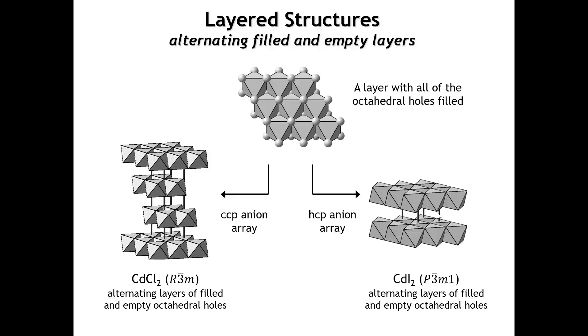In an ionic compound, filling cations in some layers but not others does not maximize cation separation, which is a clue that these are not truly ionic structures. What holds the layers together is typically dispersion forces. The anions are large and polarizable—iodide, bromide, chloride, selenide—and the cations form reasonably covalent bonds with them, meaning the anion doesn't carry a full ionic charge; it's not a fully ionic compound.